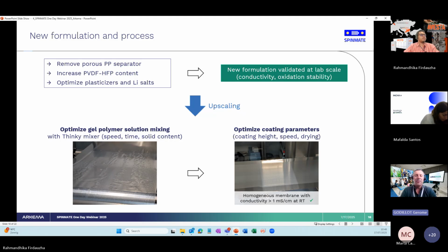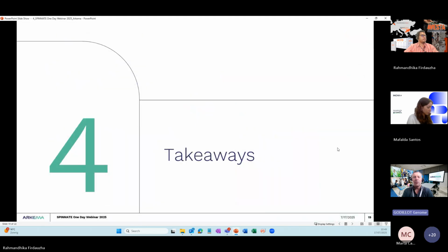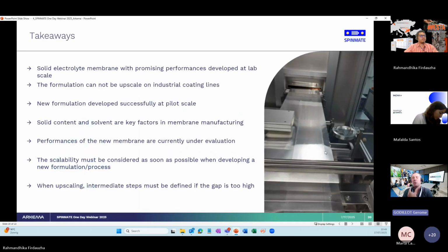So what we did was to work on the coating parameters. Also, we changed the solid content. We decreased it, because with lower solvent content, you have less solvent to evaporate at the end. So if you are still in the right range for coating, you are decreasing the risk of air bubbles. We worked on the coating height as well, and the speed, and we finally managed to have a film that is very homogeneous with good conductivity. Now the film looks good, and we are in the process of characterizing it to check that we obtain the same performance as the film made at lab scale.